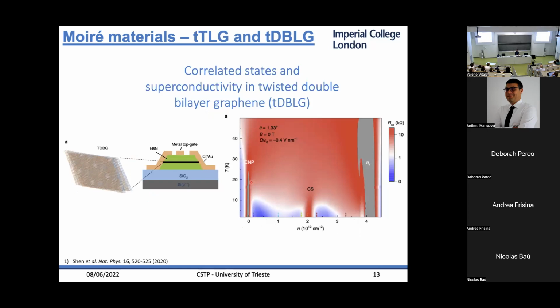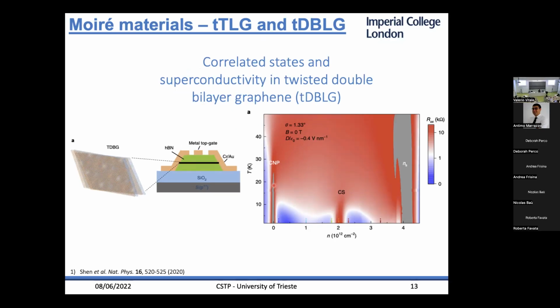Again, the same game. People played with twisted double bilayer graphene, where they put two bilayers of untwisted graphene in the AB stacking, and then they twist the middle ones. This also has superconductivity and charge insulating and correlated insulating states at different values of the angle. So graphene is basically the system that people have studied the most, but most of these correlated states, and the nature of the superconductivity, are still not quite well understood.